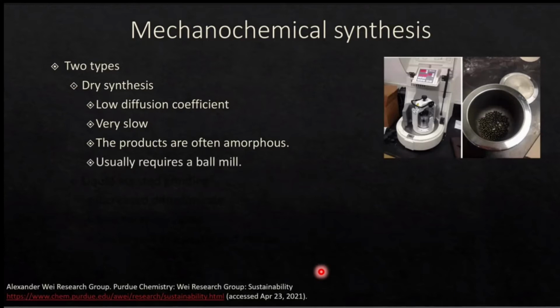So this usually requires the use of specialized equipment like a ball mill. There's a couple of other different techniques that you can use, but the general idea here is you just have these milling balls in the bottom of the chamber, and you're going to push down a piston on top of those at a specified pressure and just continue to rotate around and around and around until the reaction comes to completion.